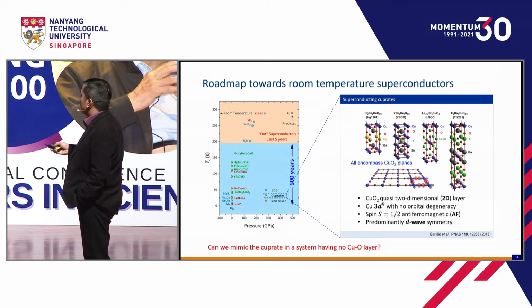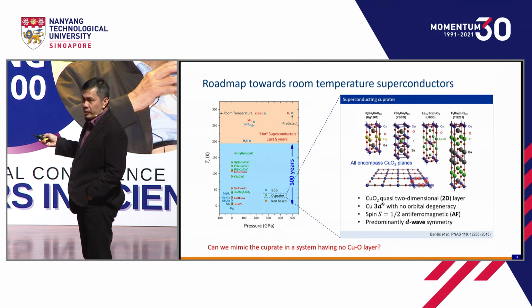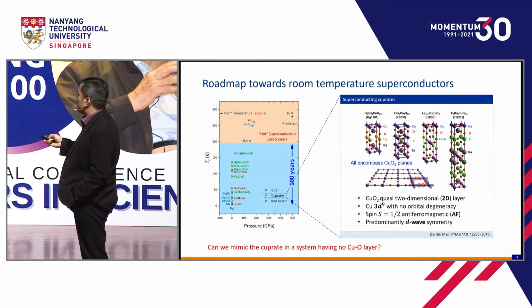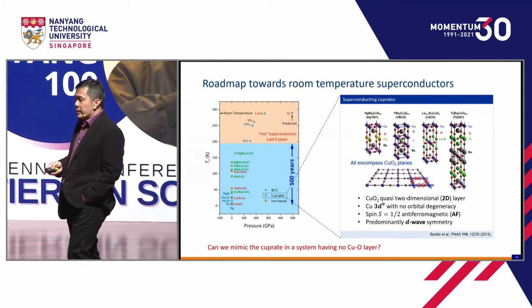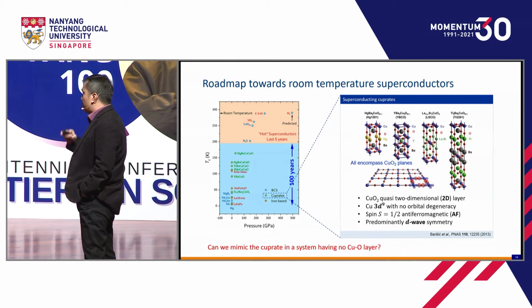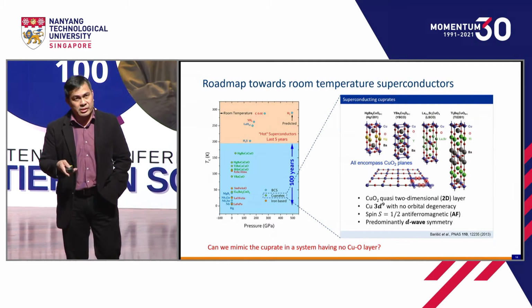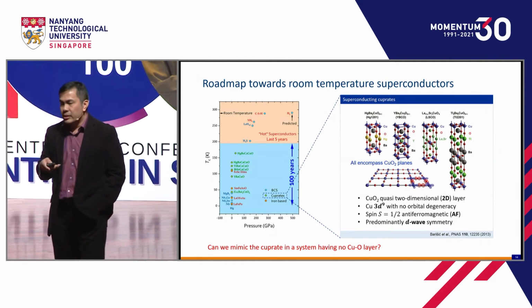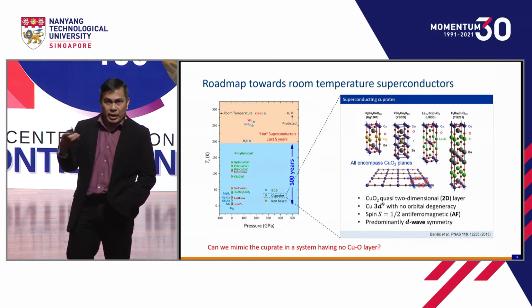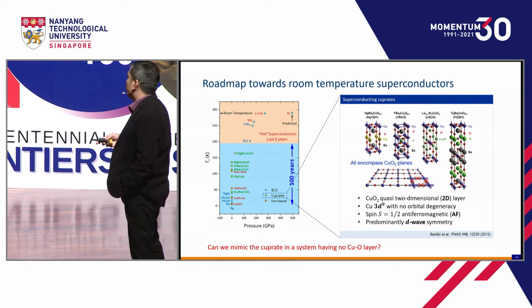What you can see here is the Tc of the superconducting cuprates as a function of pressure, right? For almost 100 years, the superconducting system at ambient pressure is dominated by the superconducting cuprates. No other compound can have a higher temperature than the cuprates. Indeed, in the last 5 years, there was a report on superconductivity close to room temperature, but it's based on hydride, and it is at a very, very high pressure, even up to 250 gigapascal, and so on, right?